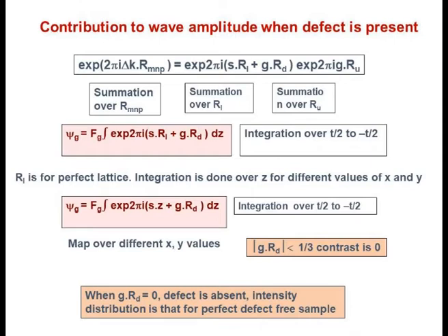That does not mean the defect is not there, the defect is there. That is why we have to image the defect under various g values. This is only for some specific g values, this will become 0. So we have to image for different values of g for which the defect is present. That is how we get a contrast. Then the value for which the defect is absent, that is what is used to find out the defect vector.